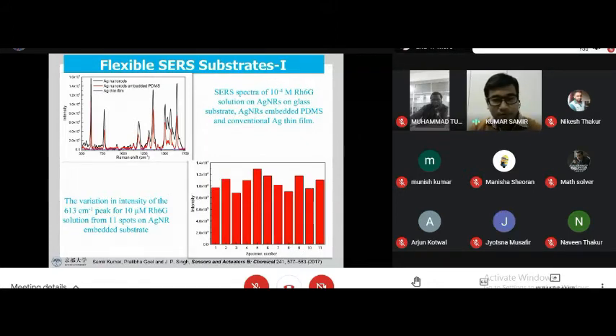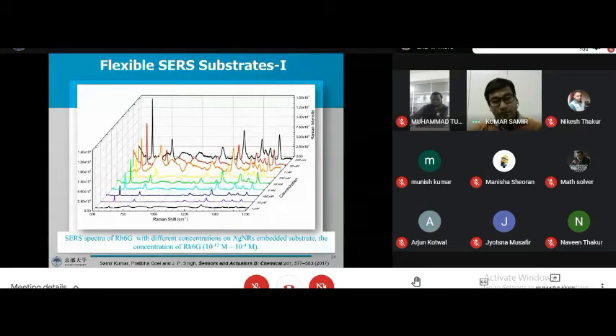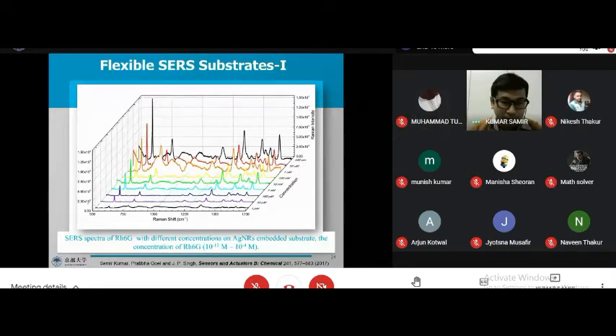And this curve shows the variation in the intensity, and we can see that it's highly reproducible, with less than 20% variation in the intensity. And it has a detection limit of 10^-12 molar. So it's highly sensitive. You can see the small peaks here, which are relatively smaller, but if you zoom in, it's quite a significant peak. It has around 10^3 intensity. So it's not that small, it's just relatively smaller compared to these peaks.